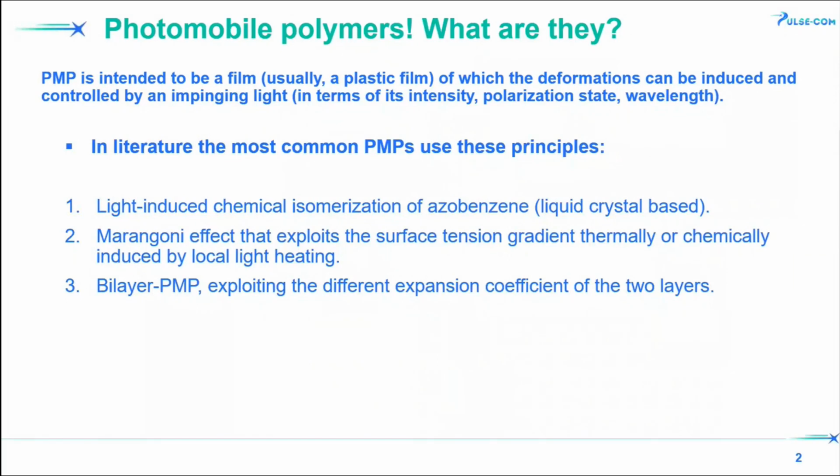You can do it at home, basically. It's very easy. If you take a piece of filter paper and put it in a ceramic filter, the one for vacuum, and you filter off a solution with some polymer with graphite, you will get this kind of material. So it's a bilayer, and the two layers have different expansion coefficients. So today we're going to talk about this kind of material.